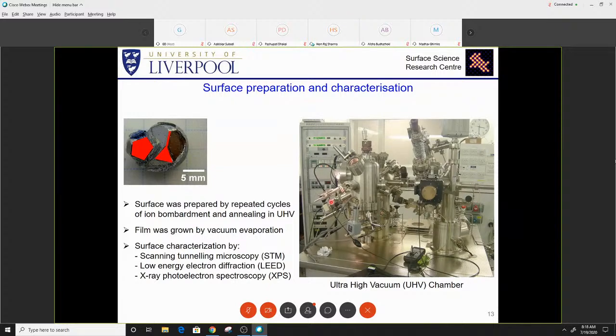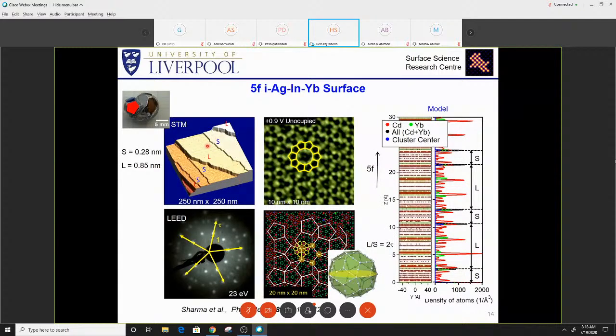I just wanted to show a glimpse. If we prepare the surface in suitable conditions, it can produce terraces as shown here. These are technically flat terraces separated by steps. The terrace corresponds to a specific plane marked in this picture. This plane corresponds to a high density plane, as the surface usually forms along high density planes. And also these planes intersect the clusters.